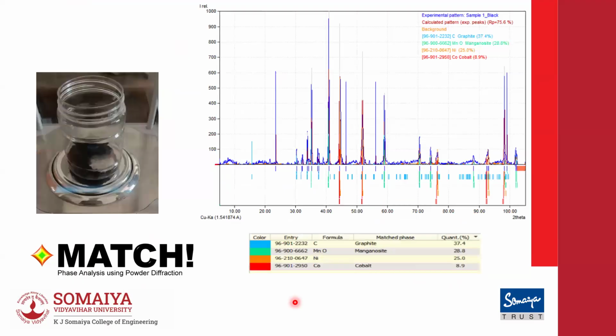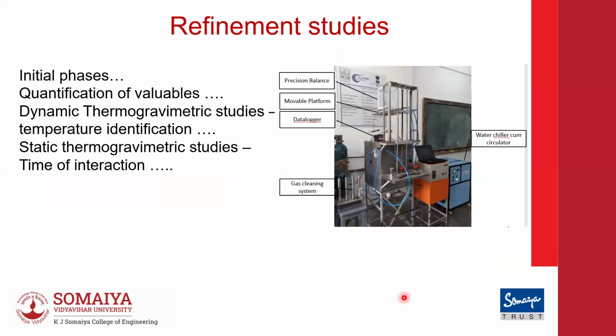For the pyrometallurgy route, we heated it up to around 800 degrees. We still have a bit of graphite there, and we have manganese oxide, which is around 28%. A bit of cobalt was also seen, which is around 9%. As I mentioned, this is a pretty old work that we have done. I put it just for perspective.